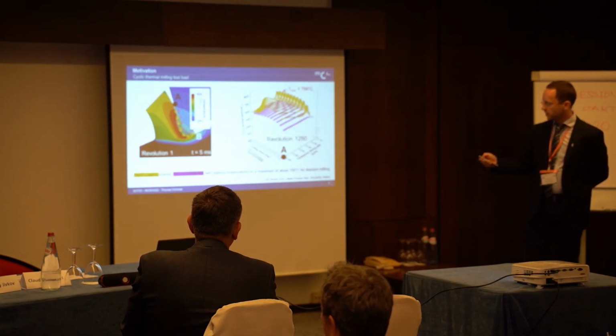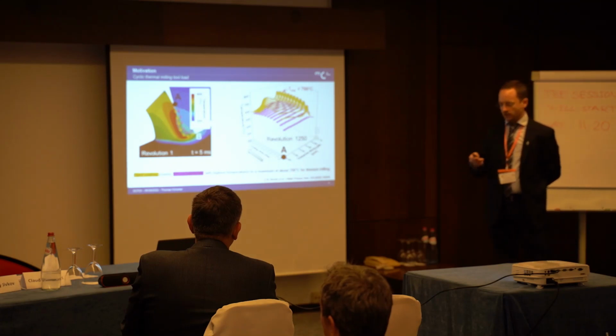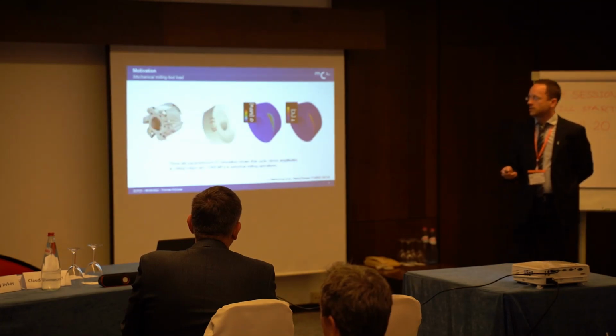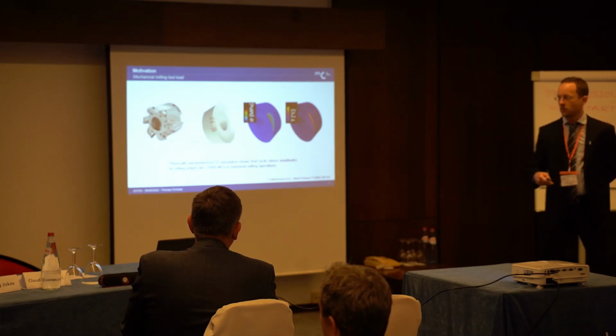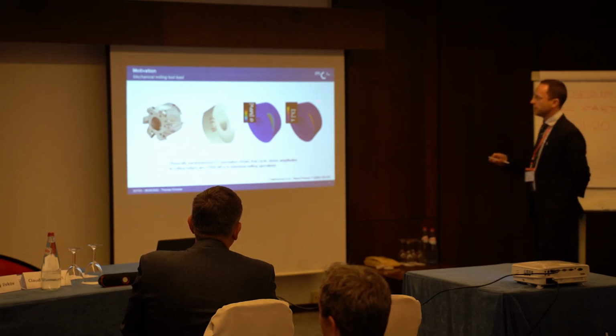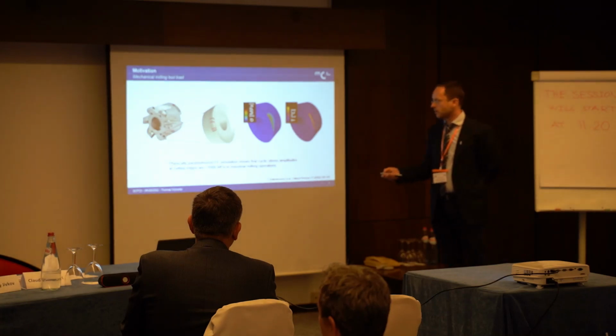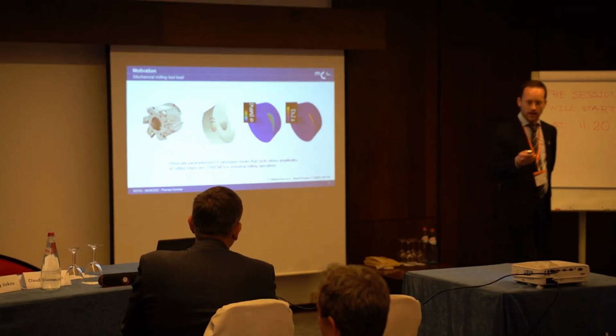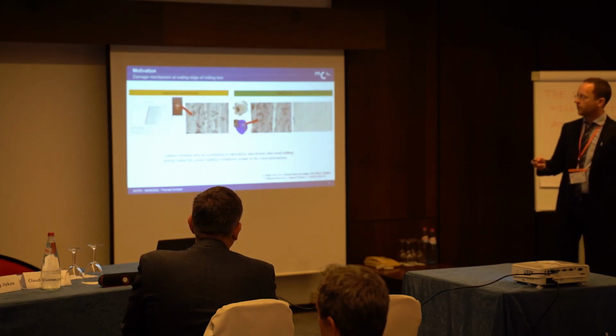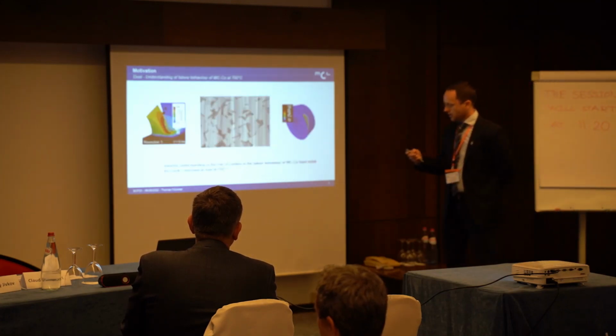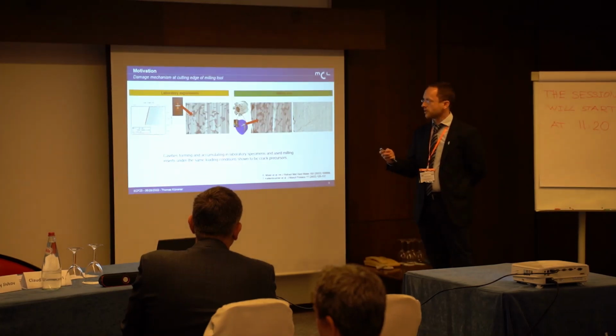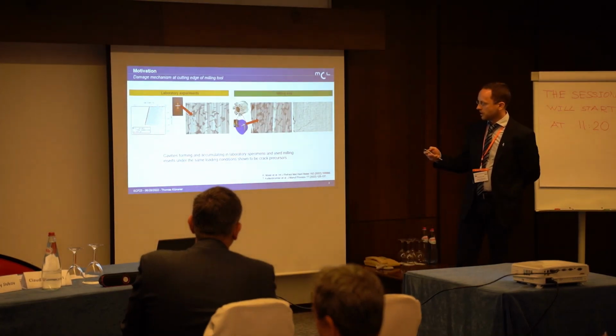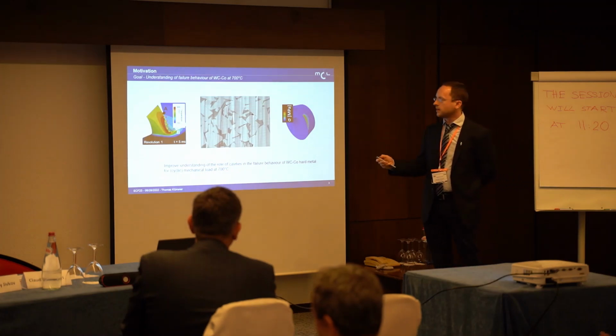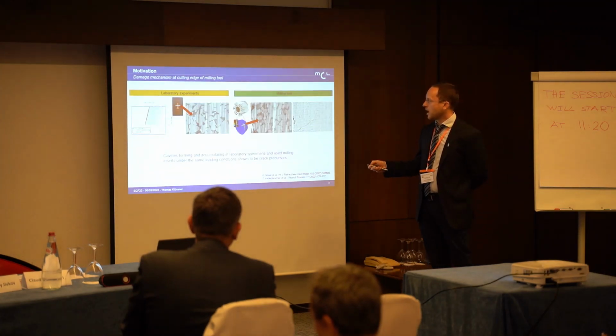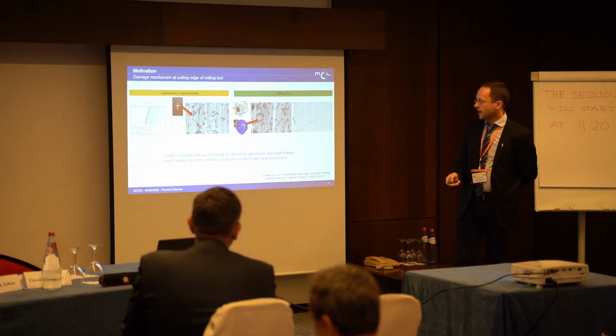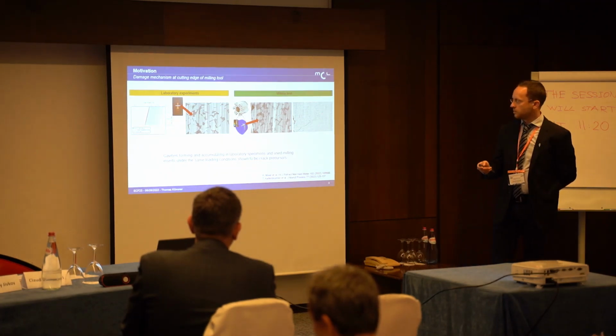and especially they're in the temperature range of about 600 to 700 degrees C. What is also interesting is that the associated stresses that we also looked into in detail are higher than thought by colleagues before, around 1,000 megapascal and slightly above. And this is of interest, and was the motivation for the work that we did, to find out that cavities and pores accumulate in laboratory experiments and that the cutting edges become crack precursors at conditions that I'll show you today in experiments in more detail.